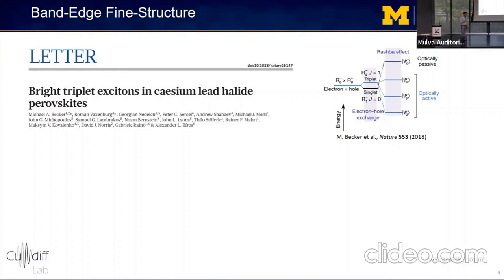And this is because in perovskite nanocrystals, there's an additional Rashba spin-orbit interaction that both lifts the degeneracy of the triplet states as well as lowers them in energy. And this was quite exciting for the whole community since this meant that excitons being generated in these perovskite nanocrystals could directly emit light instead of having to first relax into an intermediate dark state with a much longer radiative recombination time.